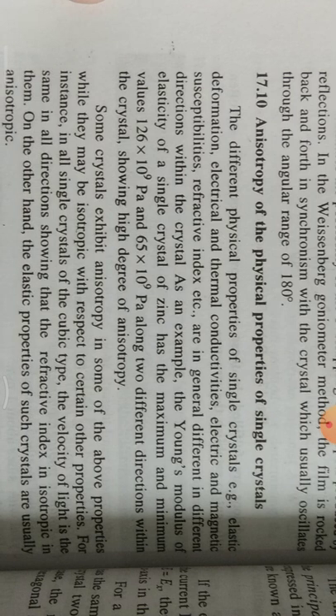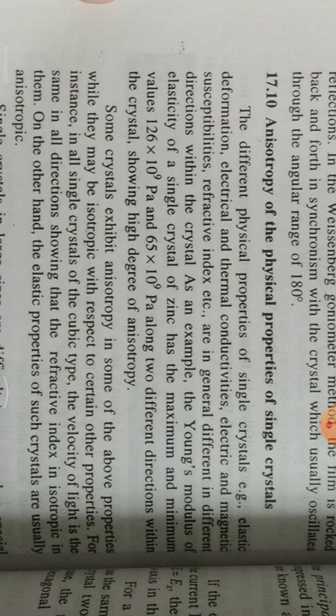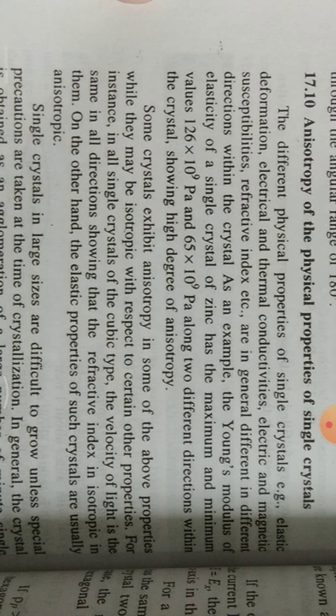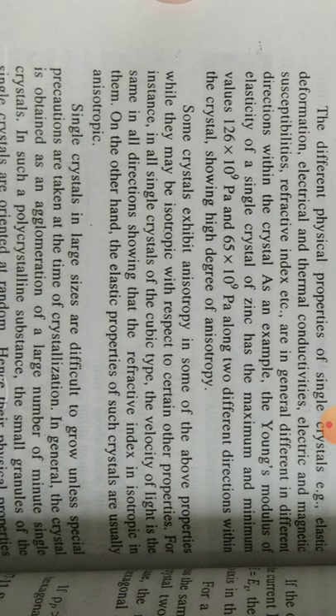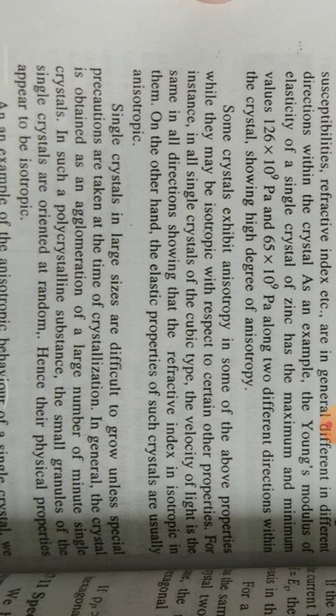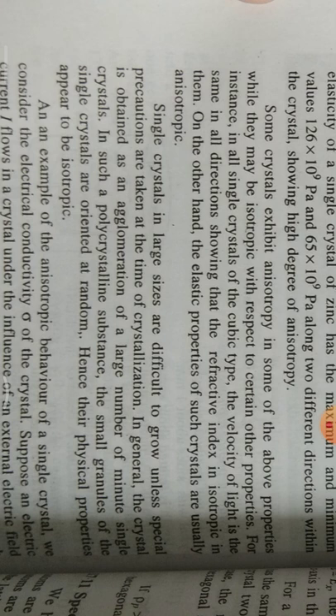Next, I talk about anisotropy of the physical properties of single crystals. The different physical properties of single crystals, for example elastic deformation, electrical and thermal conductivity, electric and magnetic susceptibility, refractive index, etc., are in general different in different directions within the crystal. As an example, the Young's modulus of elasticity of a single crystal of zinc has maximum and minimum values of 126 × 10⁹ pascals and 65 × 10⁹ pascals along two different directions within the crystal, showing a high degree of anisotropy.